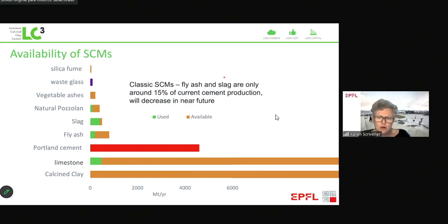Fly ash, for example, comes from burning coal, and that's the very first thing we have to do to confront climate change, is stop burning coal. So fly ash will disappear. It's already not available in many countries. And slag, similarly, this is coming from reduction of iron in blast furnaces. This is a more CO2 intensive process than making cement. And again, people are looking at alternative ways to produce iron, looking at more recycling. So the amount of slag will go down.